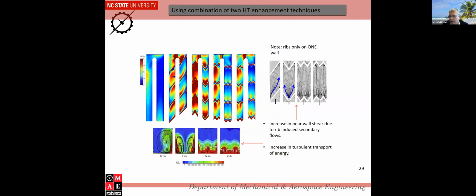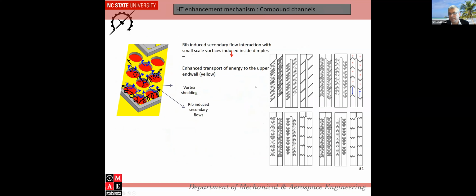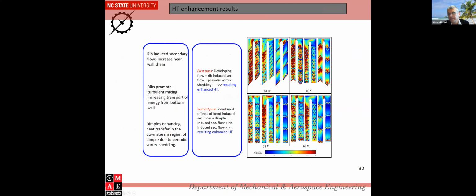I want to get into something that I'm doing right now, which is combining two different experiments using ribs and dimples. We have ribs here, we have dimples here, and dimples and ribs together. So how do you enhance it? This is my ribs only, which gives significantly high heat transfer. Then you have dimples, and you can see very localized heat transfer enhancement because of the flow going into the cavity and coming out and reattaching and enhancing heat transfer. And when you add both of them, you can see a substantial amount of red on both channels. What it proves is that if I take this and this together, I get a significantly higher heat transfer.